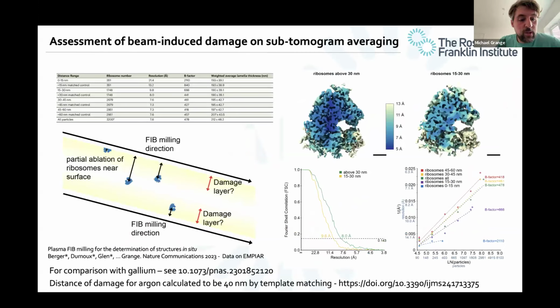trade-off might be with ion beam milling on the sample surface. So what we did was to take our 16,000 particles and then essentially bin them out into 15 nanometer bins. So if we take the edges of the lamella we produce and then plot the normal to that edge, and then calculate that distance, take those particles within that distance, and then average those separately to one another, we can plot a metric called a B factor, which allows us to determine how many particles we need to reach a certain resolution. And we did this and showed that after about 45 nanometers, the B factors don't improve.